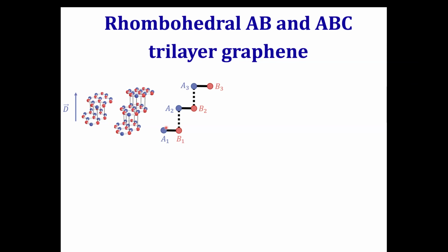It's kind of a fun exercise. If you solve this tight binding model on this type of lattice, you would find that without the displacement field, the low energy dispersion of the 2 bands originating from the 2 surfaces scales like k to the power n, where n is the number of layers. For n equals 1, that's graphene, that's linear dispersion. n equals 2 is Bernal bilayer graphene. There the band touching is parabolic. And it continues. For a trilayer, it would be k to the power 3, and k to the power 4 and so on.